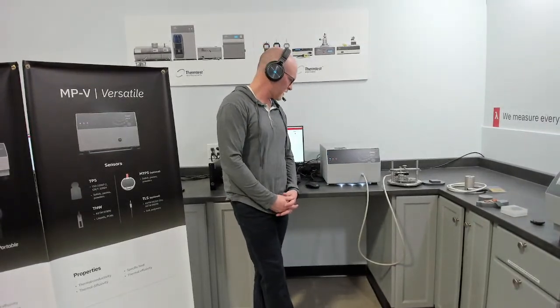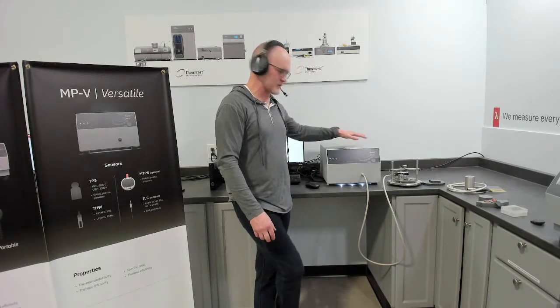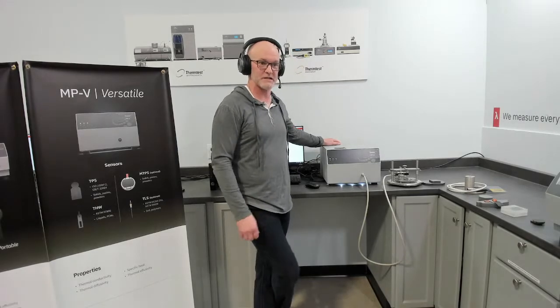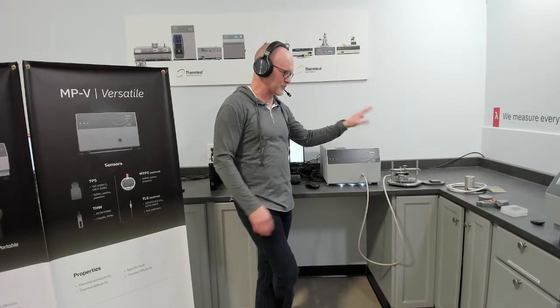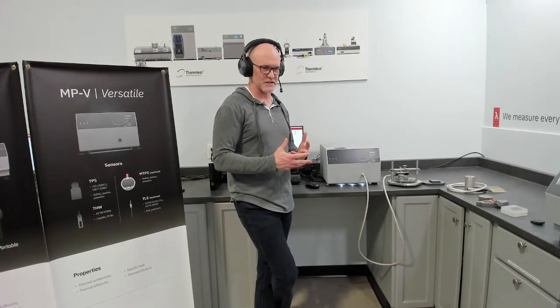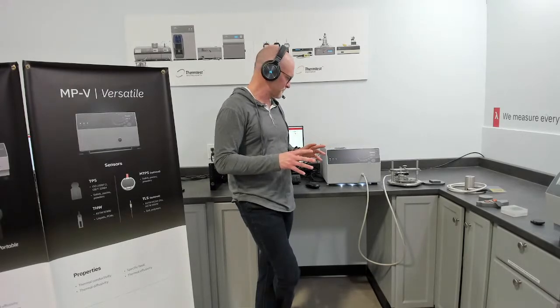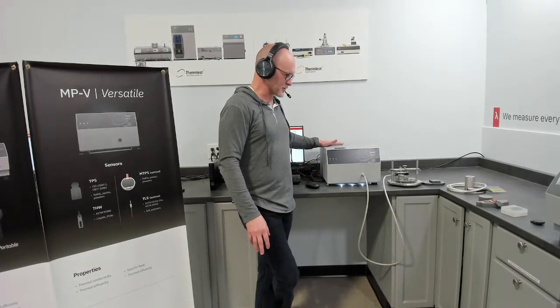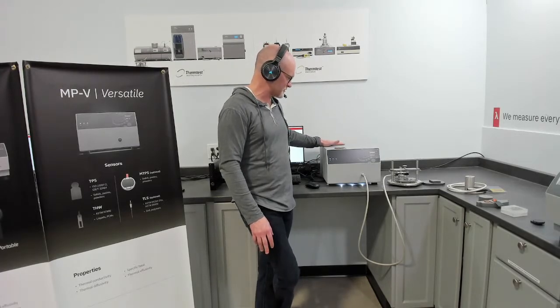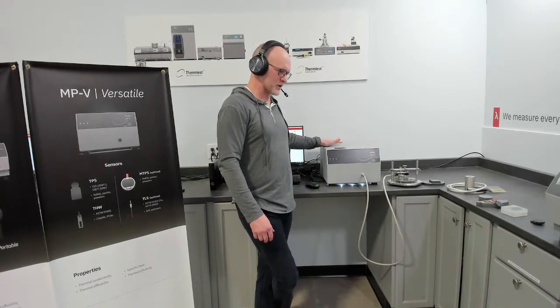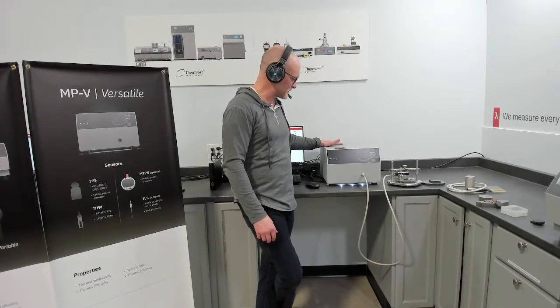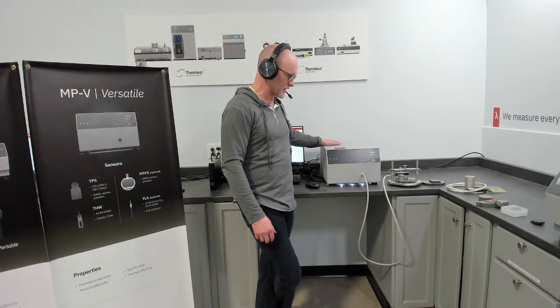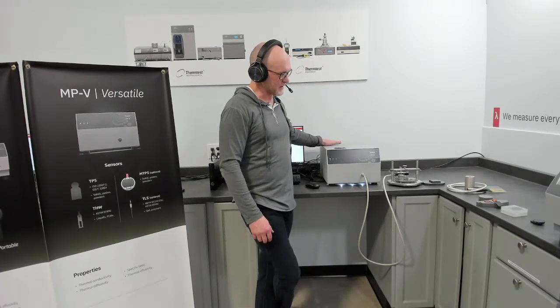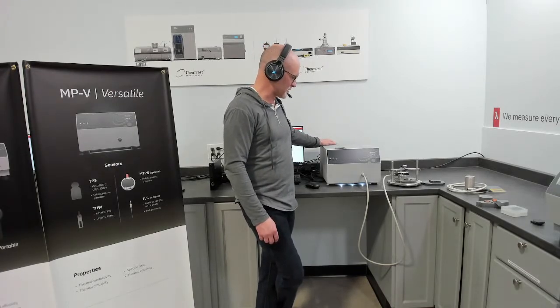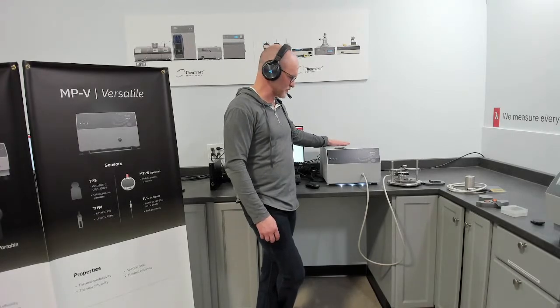So to the other side of me is our MPV, and we'll be talking a little bit about this. Again, the controller itself is going to look like a TPS-2 because it in fact is. We've just added the capability inside of it and created a package that really creates a lot of versatility in the mid-range thermophysical instrument space. So the two methods that it combines are transient plane source following ISO 22007-2. The basic thermal conductivity range for that transient plane source is 0.01 to 100 watts per meter Kelvin. That's your basic range. That can be upgraded within the same controller up to 500 watts per meter Kelvin. But the basic package is up to 100 watts per meter Kelvin.